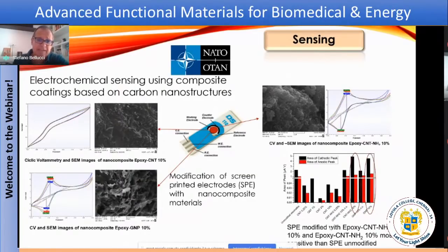Here you see an example of what we did in 2014 with a project financed by the NATO organization, the Transatlantic Alliance, USA, Europe, where electrochemical sensors were developed in my lab using composite coatings based on carbon nanostructures. We compared the effectiveness of nanotubes with graphene and with nanotubes functionalized by aminic groups. And we concluded that good sensors on screen-printed electrodes are provided only by nanotubes with aminic functionalization, but not by pristine nanotubes, nor by graphene.